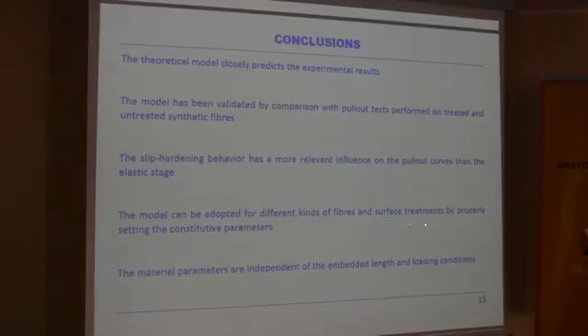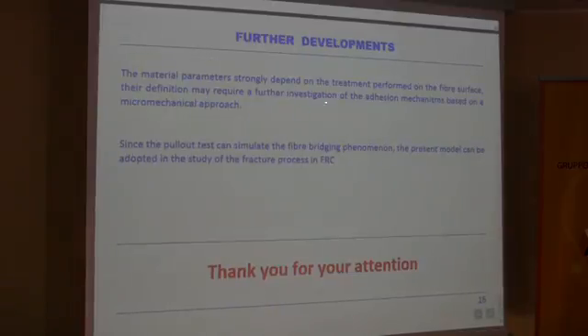And the model is able to consider every kind of fiber, just by changing the interface constitutive law. And the material parameters are found to be independent from the geometry and loading condition. However, the material parameters might depend on the treatment performed on the fiber surface. And in order to define these parameters according to the special treatment, a further investigation of the adhesion mechanism based on a micromechanical approach might be required.